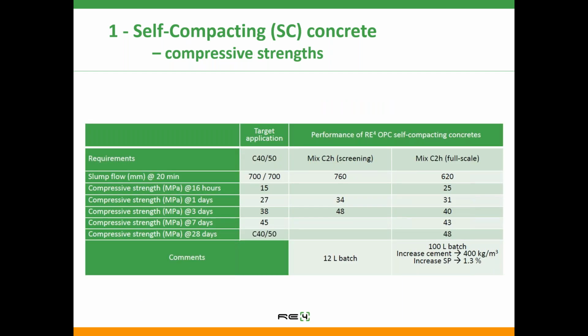Compressive strengths we obtained, as I said, there was an early age requirement at 16 hours because Crea Concrete is using it for precast work, and 16 hours is when the structural elements are lifted off the heated bed. So there was a requirement of 15 megapascal at 16 hours, and this was achieved easily. 28 days of 48 megapascal were being achieved. So some slight modification was needed to this mix to increase the cement content, increase the SP, to increase the strength further.